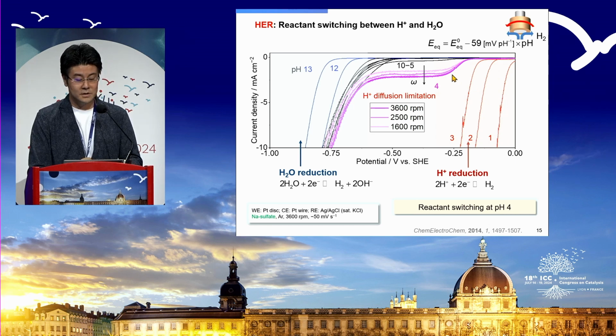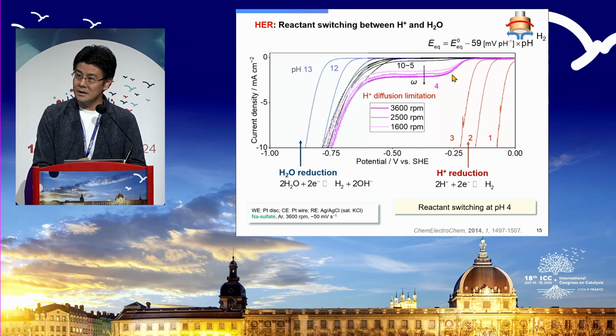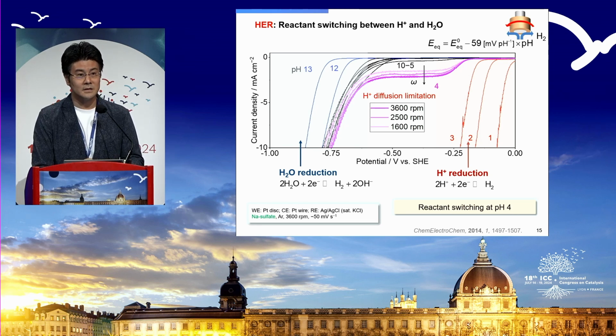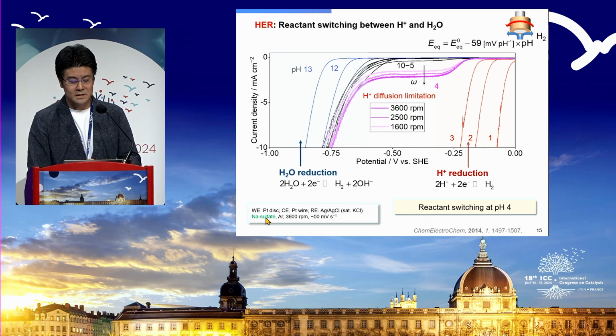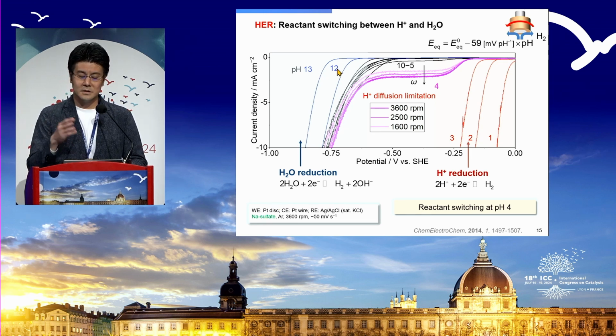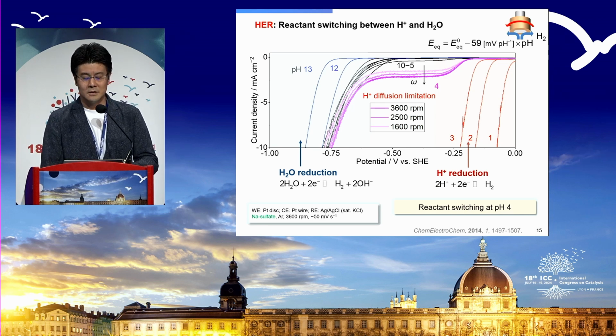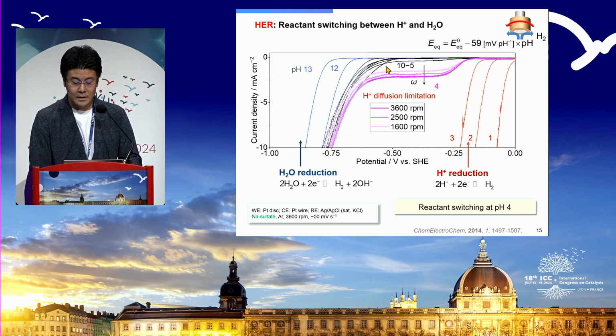Then what happens at pH 4? You no longer have enough proton concentration in the solution. Proton diffusion limitation has been observed. So you see this 10 to 5, it actually goes to the same trend because proton cannot be the reactant in these conditions. This is an unbuffered condition, so sodium sulfate is used. At 12, 13, you shift again because the thermodynamics doesn't allow you to generate hydrogen at this potential.